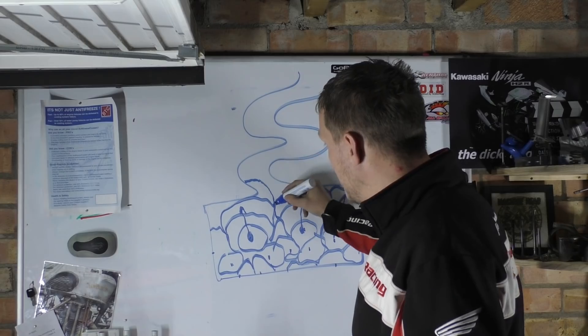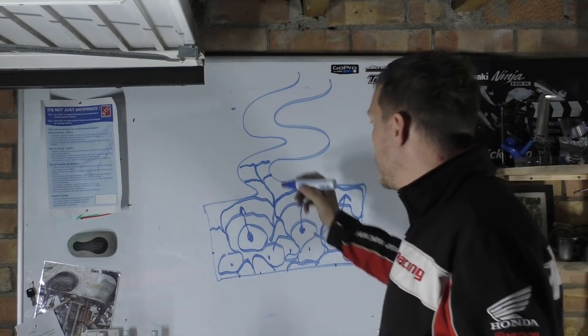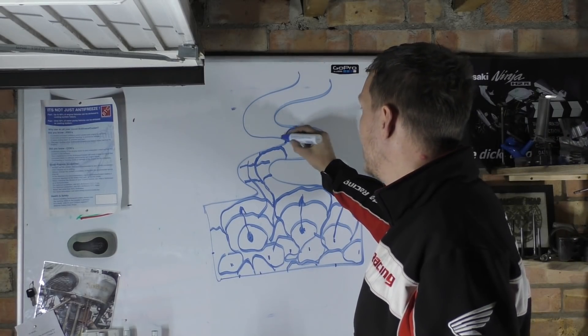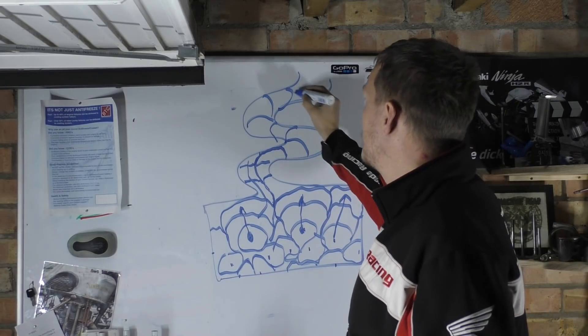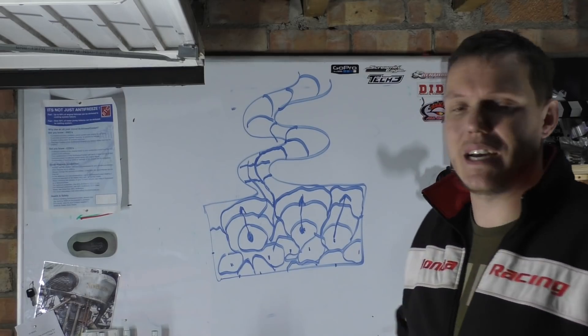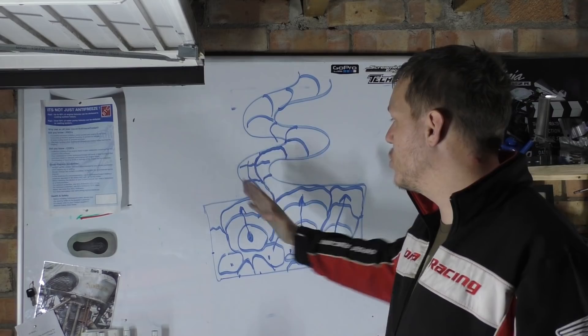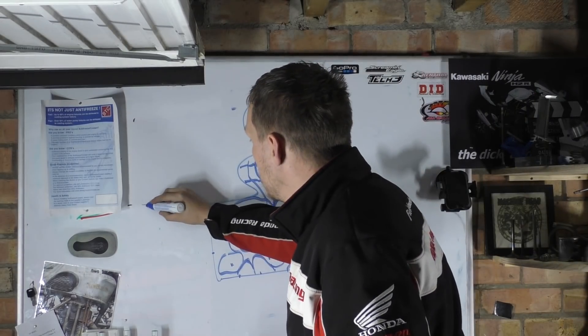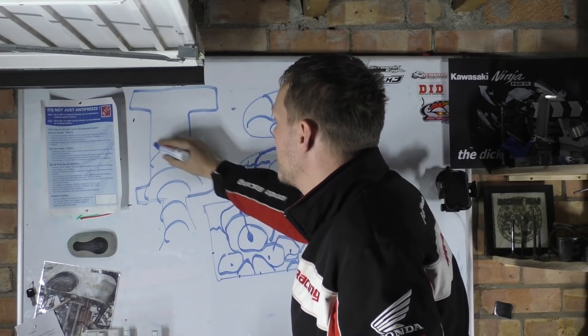So now you've got two crystals — it doesn't matter what the number is, it could be a thousand. But as you come to a radius, one grows through and the other gets choked out and stops. The single crystal, every time it comes to a radius and there's any competition, it can just basically squeeze it out. It's like having two riders on a race track — if one rider always has the inside line, he's going to be the fastest and pull away. Every time we do this meandering, every time we go around it, it's choking out another crystal. They calculate the angles needed and every time it smushes out one more. By the time you get to the top — your investment casting cavity — it is just one crystal that grows up.